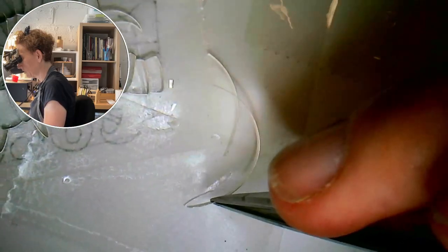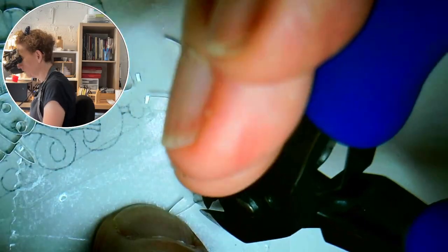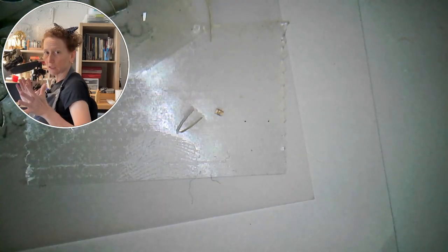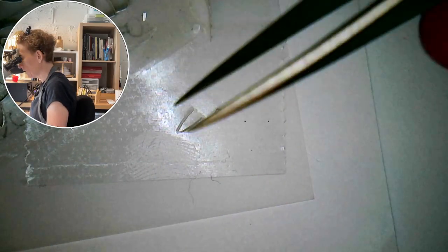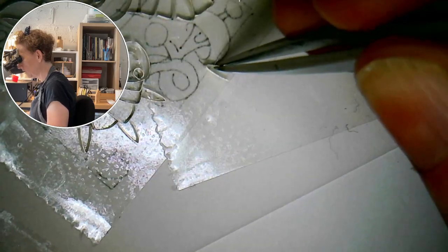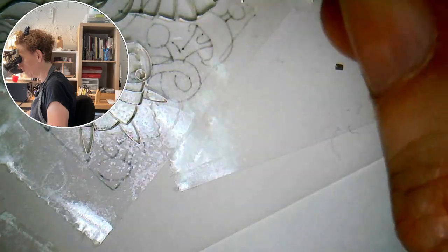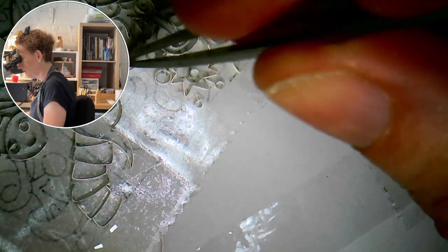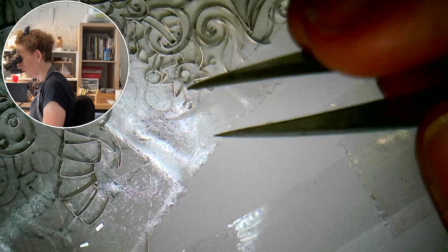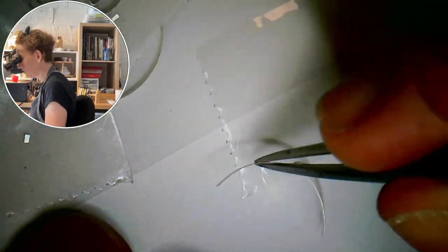depletion gild the silver, because it's sterling silver. So I'm going to do the method that Amy Roper Lyons suggested, which is to depletion gild it in the kiln, which makes so much sense. It would be heating up super evenly. So I'm just going to put it in the kiln, let it turn black, quench it, pickle it, put it in the kiln, let it turn black, quench it, pickle it, and keep doing that until it stops turning black when you put it in the kiln, and then all the fine silver. Will I do that live? I don't know. Maybe I'll do that not live, because I can't imagine that's a very exciting thing to see. So we're going to depletion gild that.